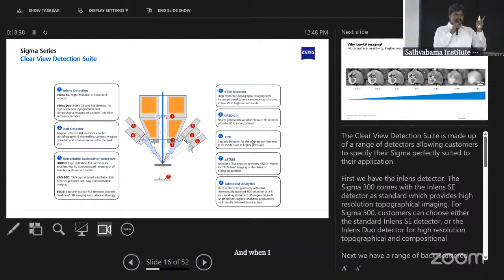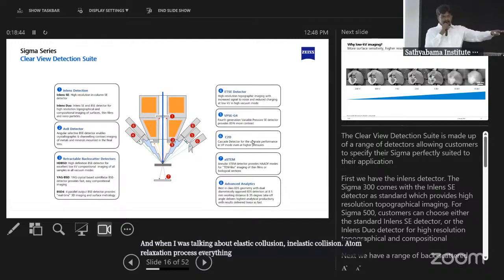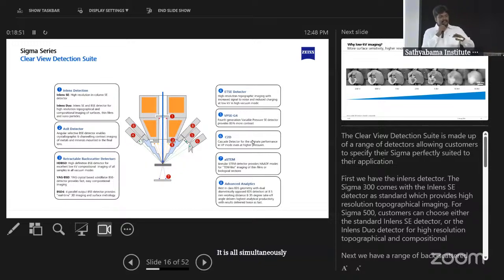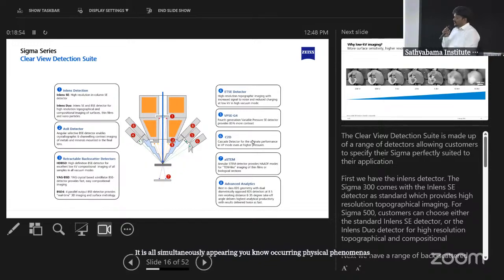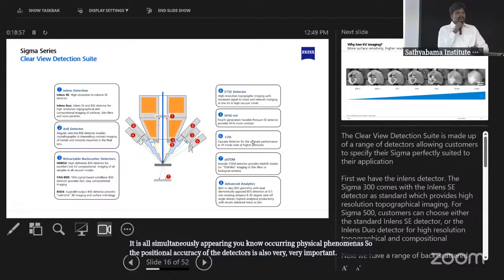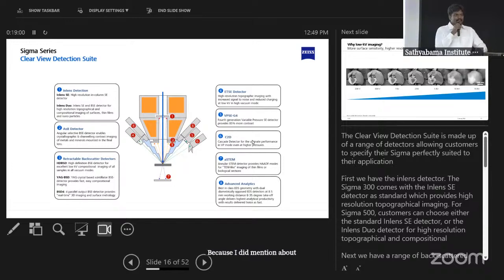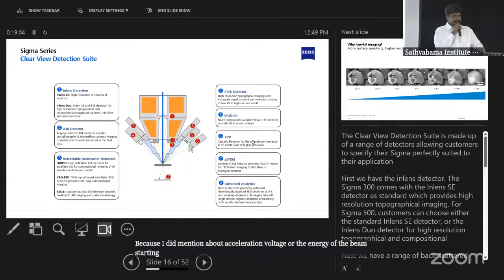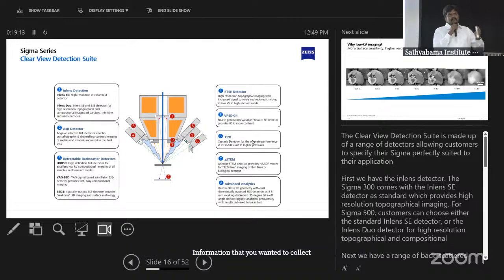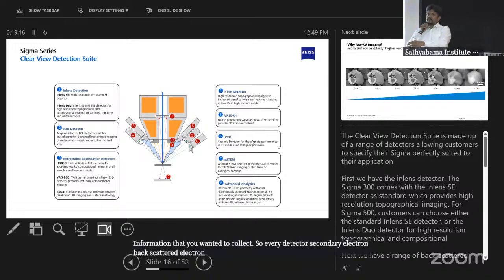And when I was talking about elastic collision, inelastic collision, atom relaxation process, everything happens in parallel. It is not a series of events that happens one after the other. It is all simultaneously occurring physical phenomena. So the positional accuracy of the detectors is also very, very important, because I did mention the acceleration voltage, or the energy of the beam, starting with just 20 electron volts. Imagine if the detectors are not positioned at the right angle, you will start missing the information that you wanted to collect. So for every detector, secondary electron, backscattered electron, chemical composition analysis using EDS, or your Auger electron, whatever you name it, the positional accuracy is very, very important.